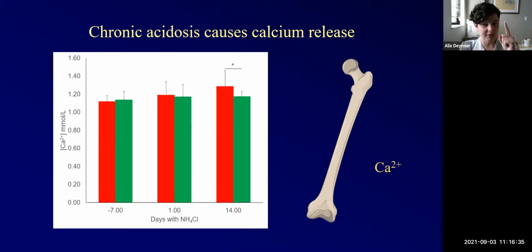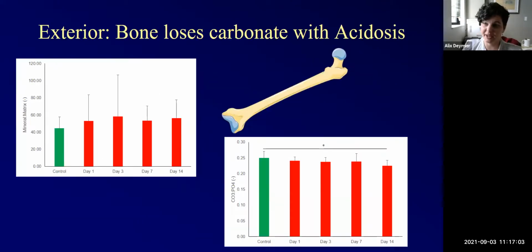So I know I've induced acidosis, and now I know that I probably have bone dissolution as indicated by the increase in calcium in the blood. Okay. If I'm seeing that there's probably dissolution, there's probably going to be changes in the composition of the bone itself. So to get compositional information, I'm actually going to go ahead and do Raman spectroscopy. And Raman's going to give us a whole slew of information, but I'm going to break it down into two main factors. The first factor that we're going to look at is the mineral to matrix. And that's telling me how much mineral I have in my bone compared to the amount of collagen in my bone. The other factor we'll look at is the carbonate to phosphate ratio.